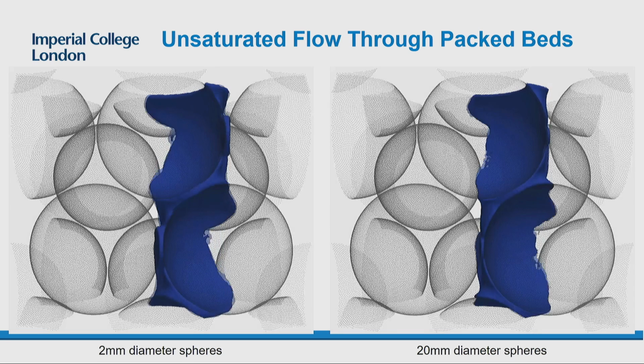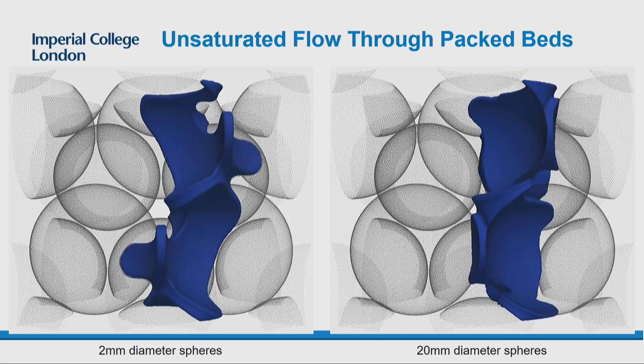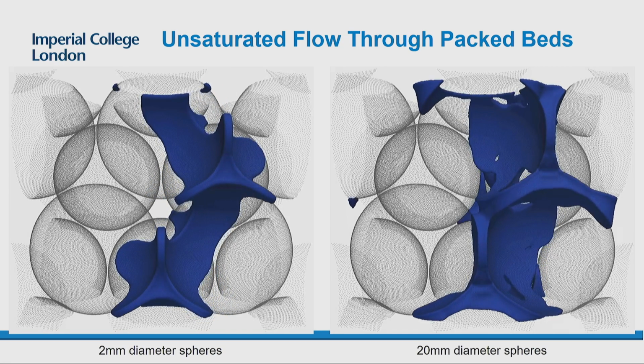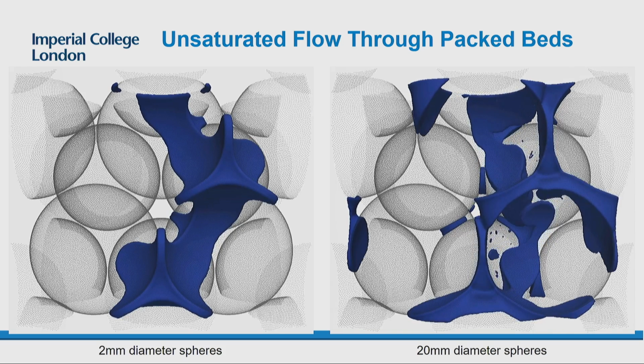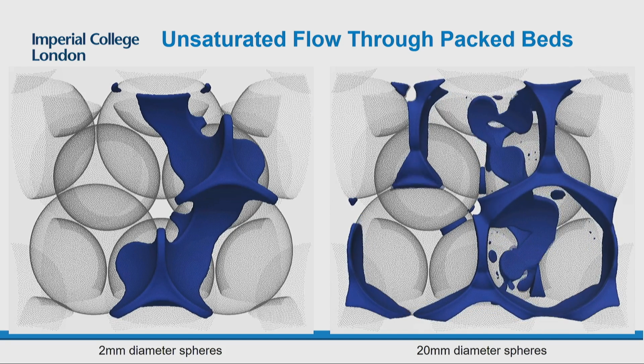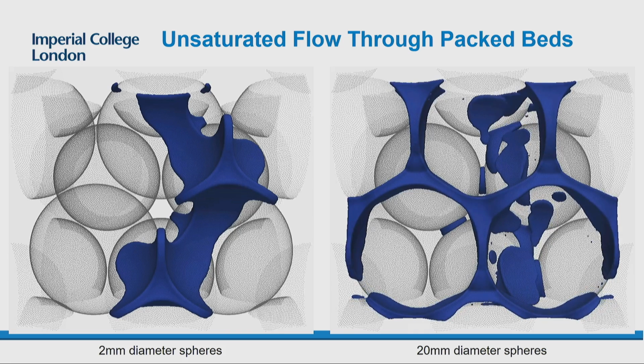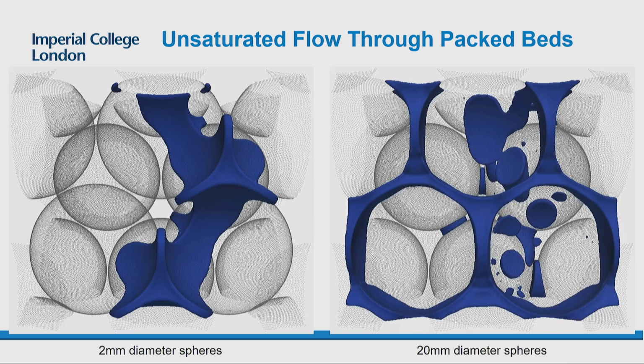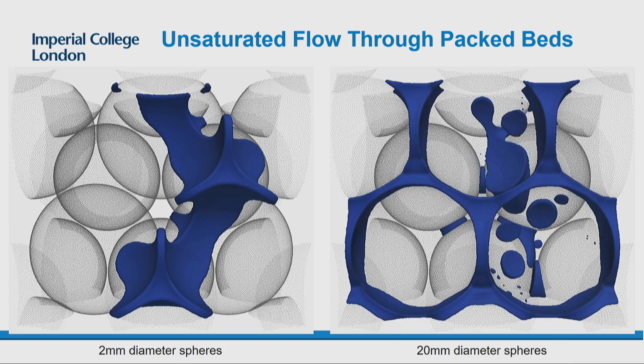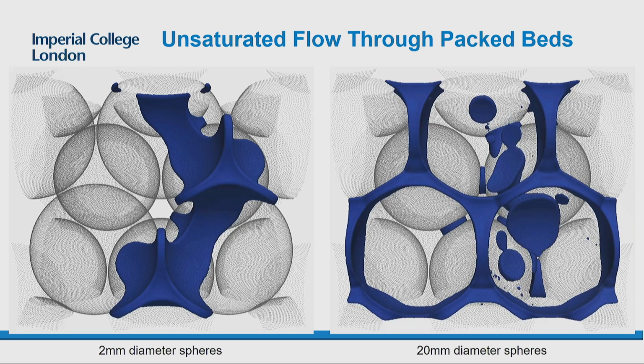The other thing we looked at is flow through this process. I'm not going to go a lot into the flow, but just show that this is an interesting system, interesting scale to start studying this at. This is simulating water flowing through a set of packed spheres, but in one side, this is through 2 millimeter spheres, and this is through 2 centimeter spheres. And these are both within the sort of range of sizes you get in heap leaching.